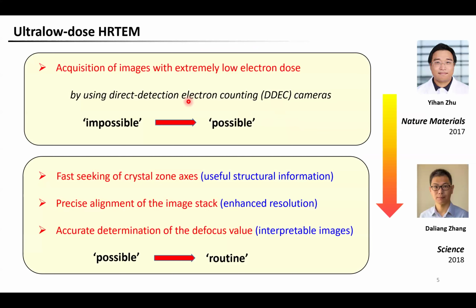So in the TEM mode, we first demonstrate that using a direct detection electron counting camera can significantly reduce the electron dose required to produce sufficient signal to noise in the image, so making low dose imaging from impossible to possible. But this is not enough. On top of this, we still need to address some additional challenges that are associated with low dose conditions. So first, because we are dealing with crystalline materials, we cannot image them from random orientations. We have to find the zone axis prior to imaging. Because we have a very limited quota of electron dose, we must find the zone axis very quickly. Otherwise, the structure will be damaged during the zone axis searching process, and we will not have any chance to take an image at all.